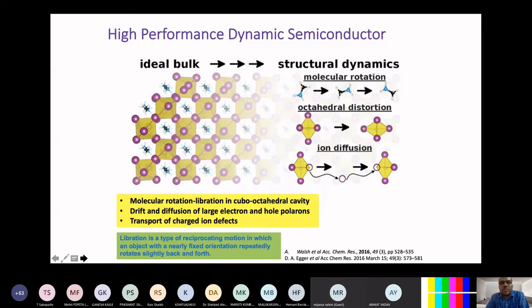So the high performance dynamic semiconductors, I'm using the word dynamic because, as I was telling, there is something constantly moving. There is nothing static in halide perovskite. This methylammonium ion is constantly rotating in this octahedra, and that is disturbing them. So there's a molecular rotation that distorts the octahedra, and some of the time this gives the energy, and some of those iodine ions get released and go to the other octahedra. So there are vacancies of the iodine ion.